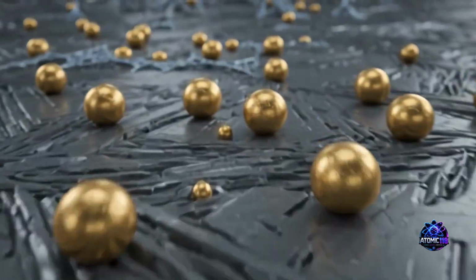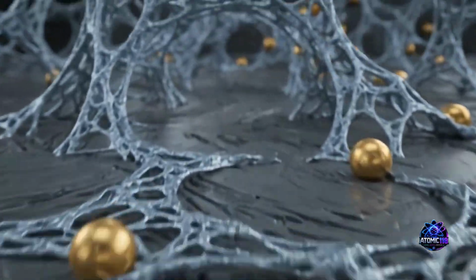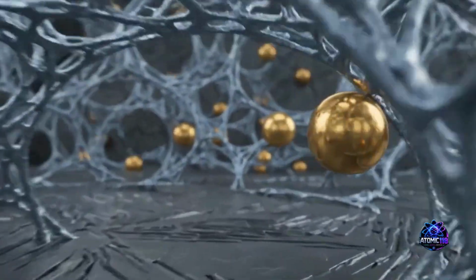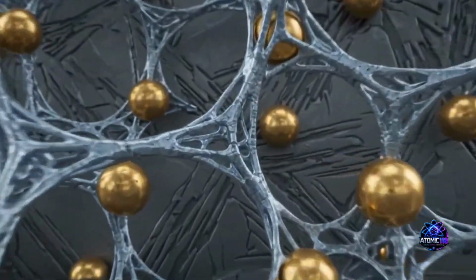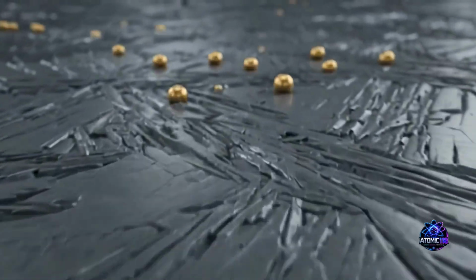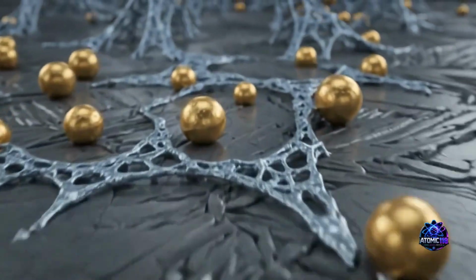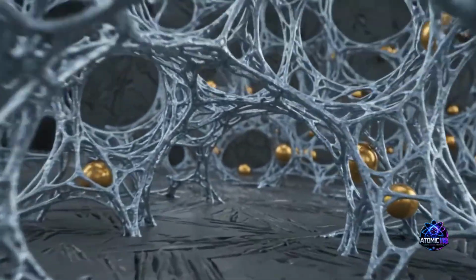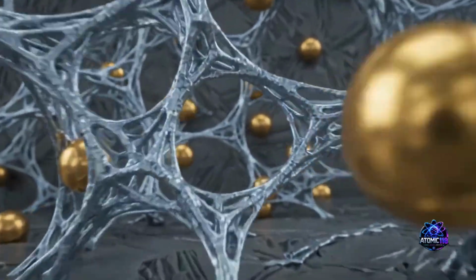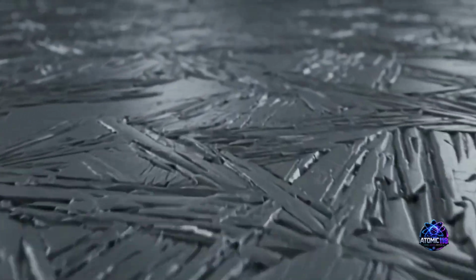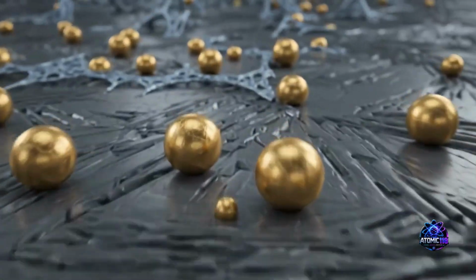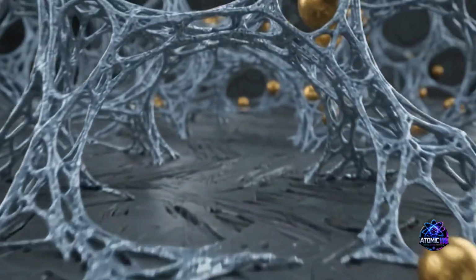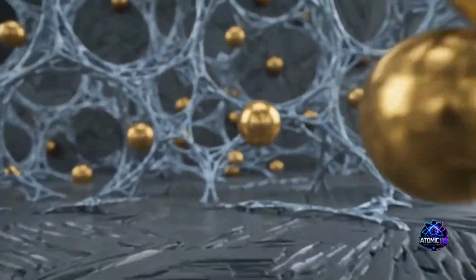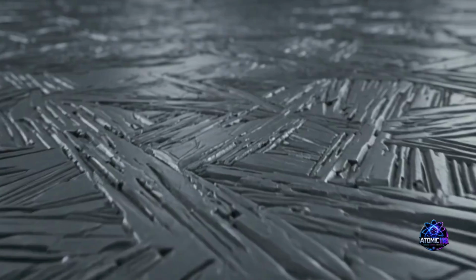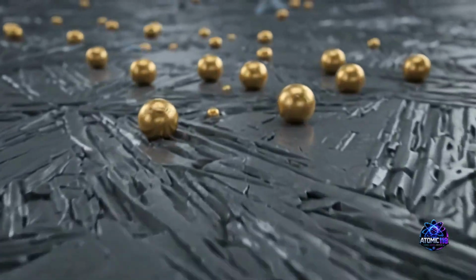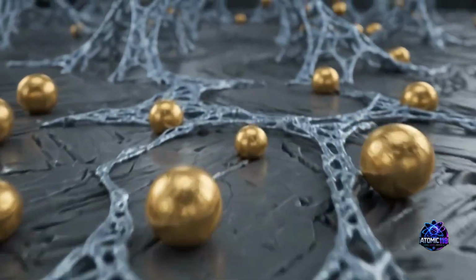Right, so centrifugal casting involves pouring liquid steel into a mold that is spinning at high speeds. Like a centrifuge. Exactly, using centrifugal force to shape the cylinder. The problem is physics. Tungsten is incredibly dense and heavy. So when they spun the liquid steel, the tungsten caused specific gravity segregation, meaning the heavier elements were thrown to the outside edge of the spinning mold, leaving all the lighter elements on the inside. Which destroyed the uniformity of the alloy. You would end up with a mill roll that was ultra-hard on one side and dangerously soft on the other. It was a complete manufacturing nightmare.